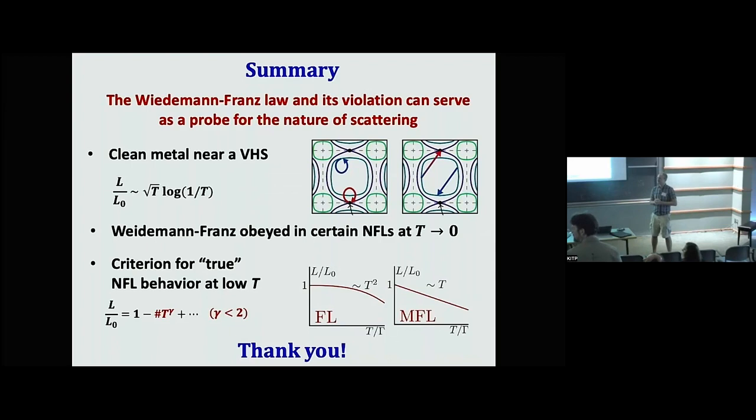About exactly the same question. Basically, what you said, that at zero temperature scattering is elastic, is not enough. At the same time, it's important that the self-energy does not renormalize the fermionic dispersion. This is sigma of omega. If it does, then you can violate. I don't know if you know an example where it was computed, where the self-energy has a singular K dependence and you find a violation all the way down to zero temperature, even though I think it's possible.